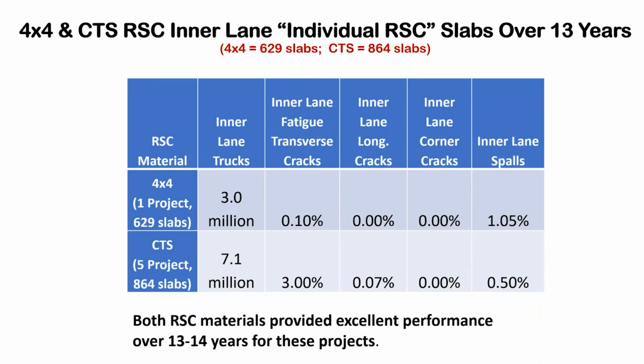And for the CTS, 5 different projects exist here. And it had a heavier truck traffic. That's the difference. So it's not a fair comparison. And you can see the consequence of that is a little bit more fatigue cracking. And you've got 0.07 and almost 0 amounts of other distresses. So I concluded, based on this data, there's really no difference here. Both of these products are performing very well and giving excellent performance over 13 or 14 years.